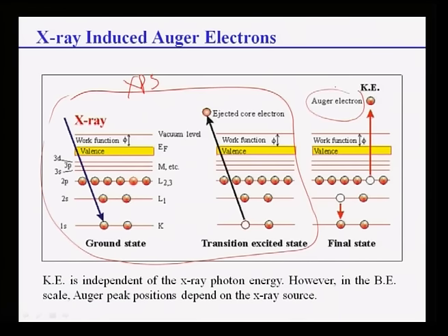Okay, so for a multi-element system, such as a surface layer, which is normally the case, we can write down the concentration of element Ni as Ni divided by Ni plus Nj plus Nk, where I, J, K are three elements. So this is how it is done: Ii divided by sigma I by lambda I, the whole divided by this sum. This is for I, this is for J, this is for K. The factor K has been nullified because of taking the ratio. So that is how it is done. I can also calculate Nj now, Nj divided by Ni plus Nj plus Nk. Similarly, Nk can be calculated. Let us see how these are done.